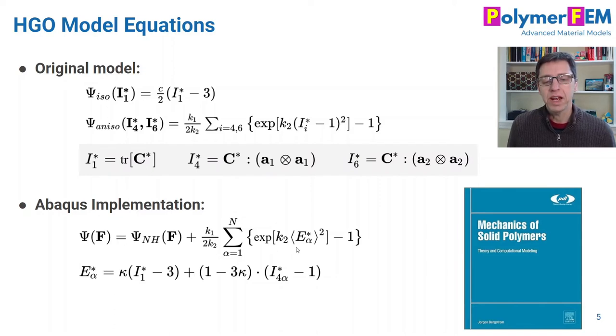And finally they put these brackets on this, which means that the quantity inside the brackets becomes zero if the argument is zero or negative. So this means that in the Abaqus implementation, the fibers don't have any stiffness in compression, but in the original paper they do.